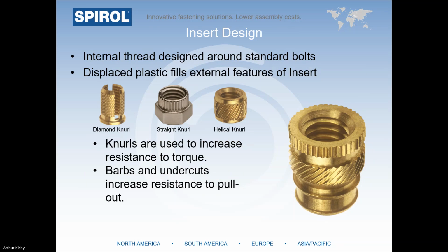Now, the internal threads of inserts are designed around industry standard metric and inch bolts. Performance of the insert is generally achieved based on the amount of displaced plastic filling the various types of features of the insert. There are typically 3 different types of knurls: diamond, straight, and helical, and they are primarily used to increase resistance to torque. Straight knurls have the best resistance to torque since they are perpendicular to the force, whereas helical knurls provide resistance to both torque and pullout, as they are at an angle. Finally, diamond knurls, well, frankly, they aren't good for anything, really.